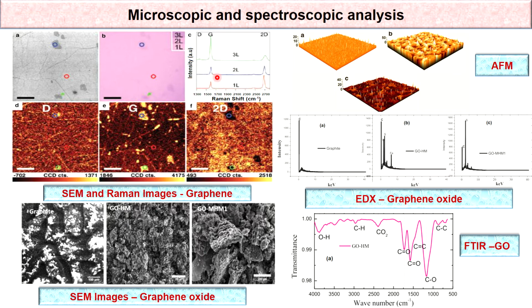graphene film. The Raman spectrum from the lightest pink background indicates a monolayer graphene. And this blue colored circle indicates the bilayer graphene, and this green color indicates the trilayer graphene. The same image demonstrates the thickness variation more clearly. Here we can see the green, pink and the blue circles, which indicate the monolayer, bilayer and trilayer graphene